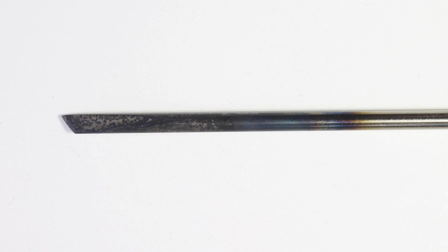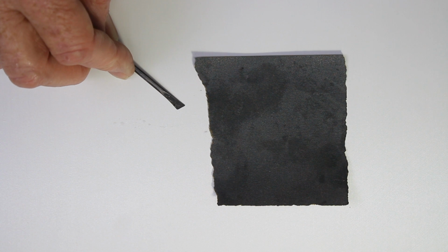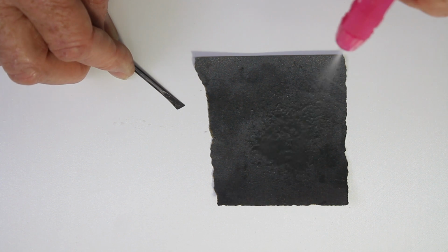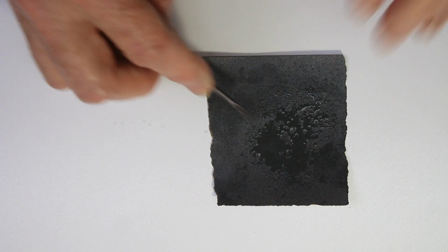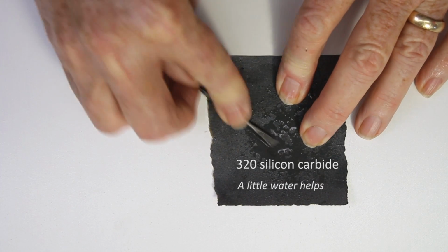The blades will be gray to black in color. Part of this is burnt oil from the first quenching. The rest, however, is a very thin layer of oxides of iron, and it's quite hard, and it clings tightly to the steel. You have to use abrasives to remove it. I rub it briskly with 320 wet or dry silicon carbide paper. Get all the black off, leaving a shiny, bright surface everywhere.